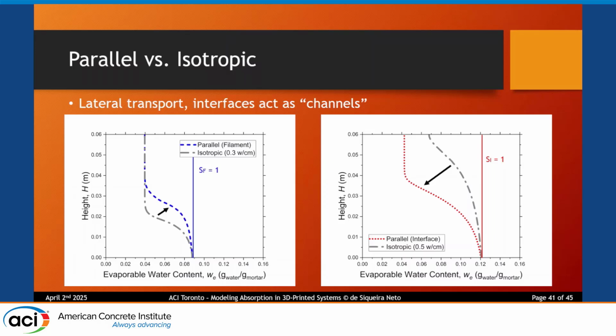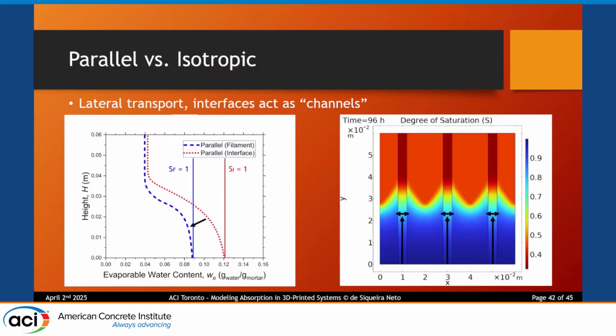And to talk just a little more about that, on the left, I've included the curves for both the filaments and the interfaces when the layers are arranged parallel to the absorption direction. And you can see that as the height increases, these curves come closer together as further indication that there is this lateral transport from the interfaces to the filaments.